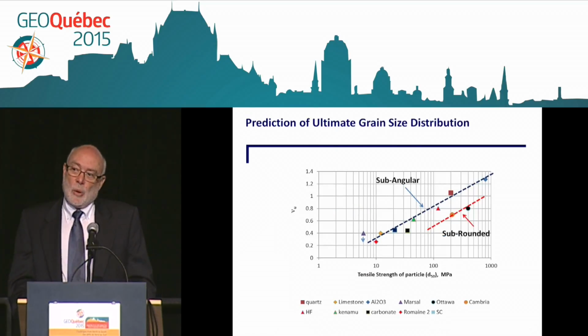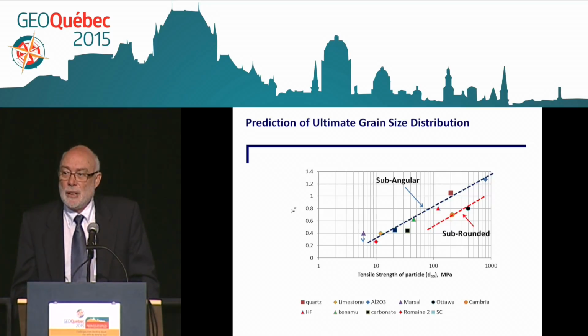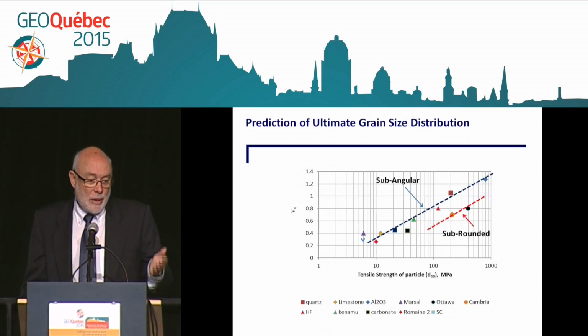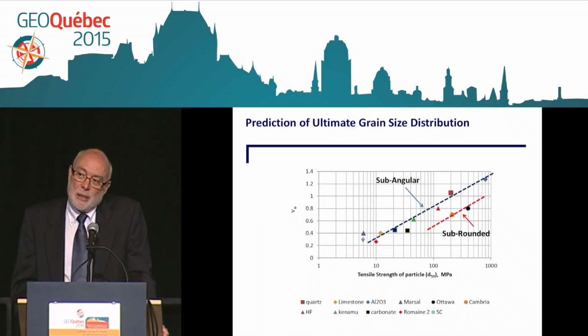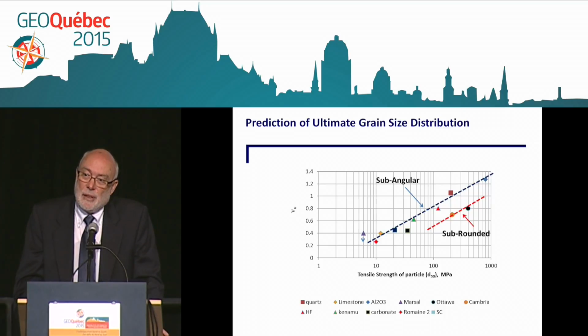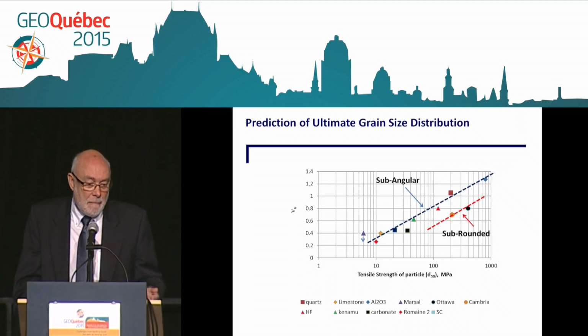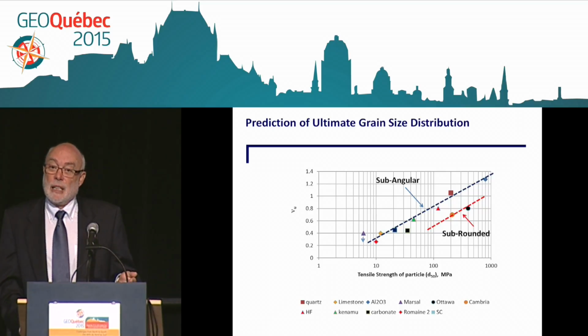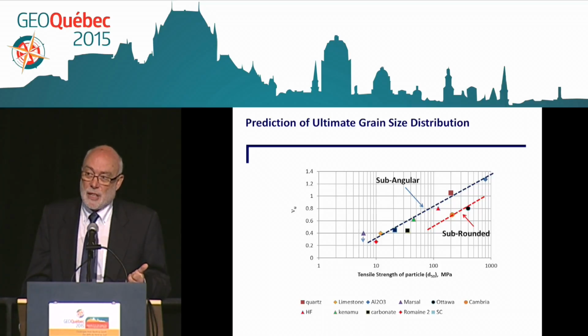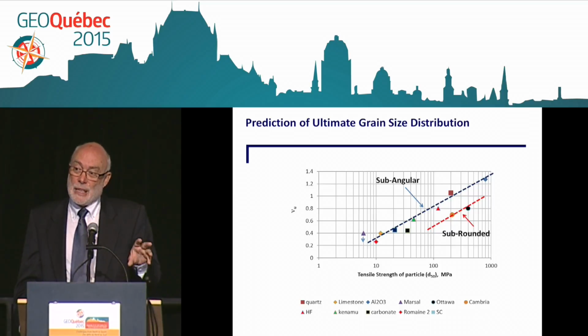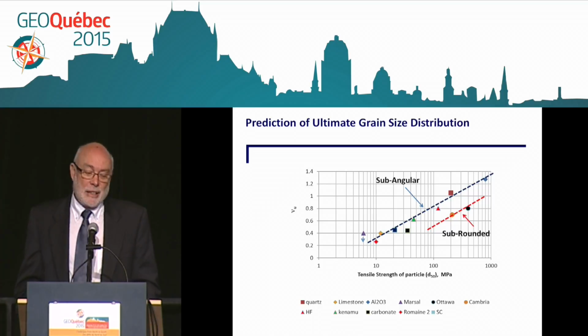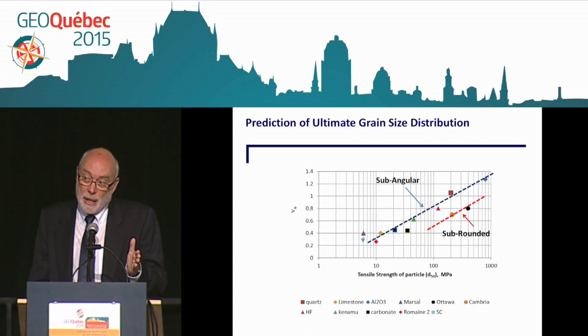We went back to all the data we did ourselves and the ones we found in the literature, and have shown that, in fact, the slope of that ultimate grain size distribution in a log-log plot can be related to the tensile strength of the particle of the rockfill. So we see that as the strength is increasing, now strength can increase for two reasons, either because size is decreasing or because the mineral is stronger. So this is an interesting plot because it has these two effects combined, but we see that the stronger the particle,